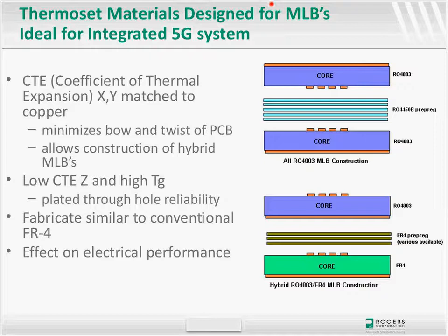We find that when we do hybrid constructions of RF materials with FR4 materials, usually the fault lines or breakpoints, when we're doing extreme thermal cycling, typically happen more in the FR4 than with materials that have around 80, 90 parts per million, versus materials that are around 40 to 50 in the Z-axis value. The other area that's important is the selection of a bond ply, basically the bond layer that will adhere the various layers here.